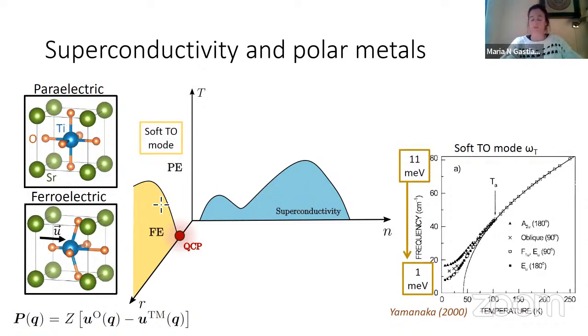And if this symmetry is broken when there are no carriers, this is a ferroelectric. If you have added carriers, there is still a polar axis that develops, but then there is no net polarization because the electrons will be screening all that out, and then you would have a polar metal.